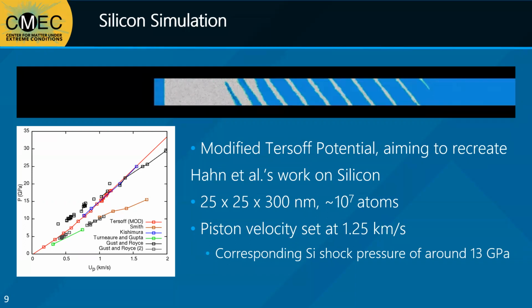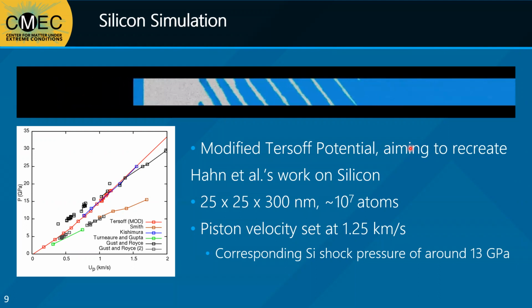amorphization in silicon. In the simulation, the blue atoms are recognized as diamond cubic. Light blue or green mean that they are first or second nearest neighbor diamond cubic, and the white color means that they are in an unidentified phase. We see angled bands of this unidentified phase propagating throughout the silicon bulk after the initial elastic wave has passed through.